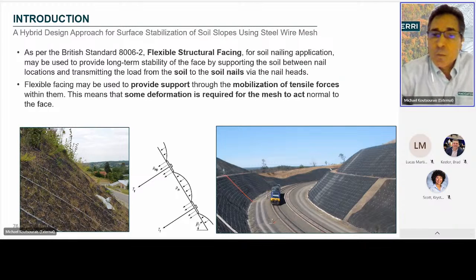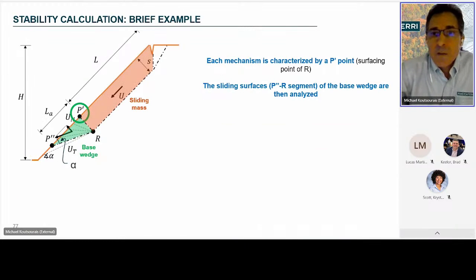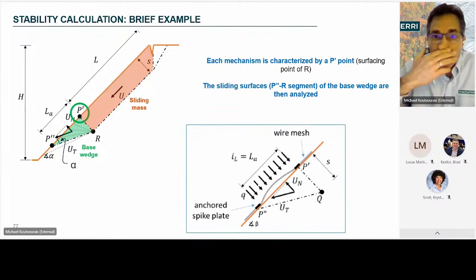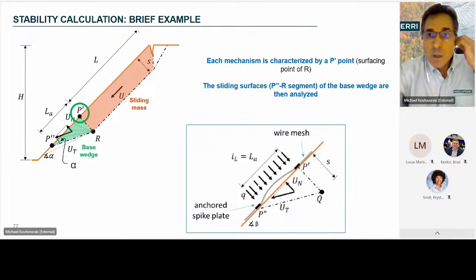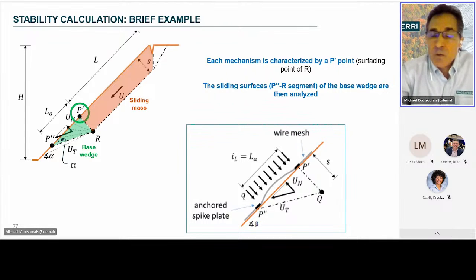Flexible facing may be used to provide support through the mobilization of tensile forces within them, and therefore some deformation is required for a component of these forces to act normal to the face. In the design of flexible facing with soil nails, a two-part wedge method of analysis is considered, where the maximum unstable volume of soil is calculated, and the result is a sliding surface close to the slope face. On a post-intervention stability analysis, a pressure Q imposed by the mesh is then introduced to increase the initial safety factor.